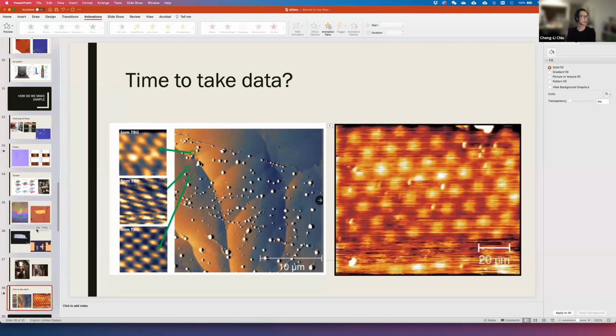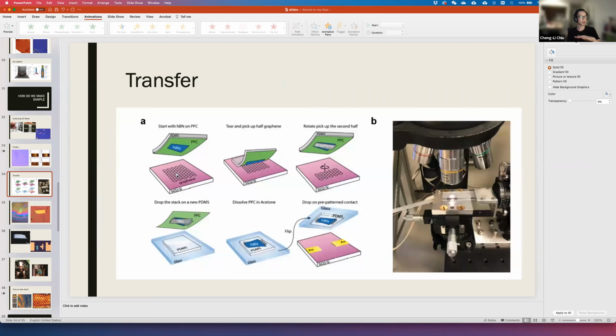So we don't do transport, but the thing that's different between STM and transport is that STM needs to use a tip to probe the surface of the sample, so you can't have anything covering your sample. You have to expose your graphene. So when you are making a sample, when you pick it up, because you cannot protect your sample using, say, another layer of hBN, your graphene must touch some polymer, and that's the reason why it becomes dirty.